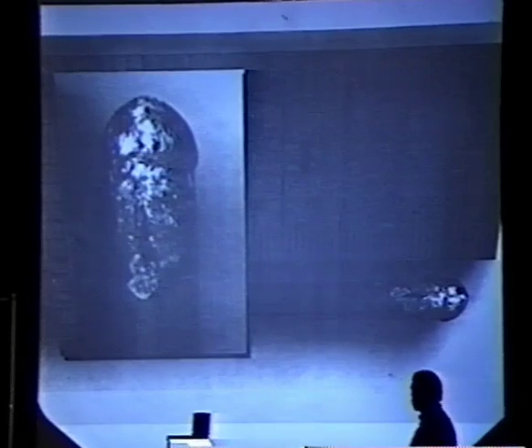That was probably better. These were made electronically, which isn't my choice, just as I left. But basically, this is the cathode. It's something like 5 centimeters long, 4 millimeters in diameter. And although you can't see it at all, this is the rupture. The cathode distended, blistered, and voided at this point, not associated with the weld at all. It's beyond the weld, although it might be in the heat-affected zone. We simply obtained a pressure inside this cathode which was too great. The cathode yielded at a pressure somewhere between 3,000 and 4,000 atmospheres of D2.